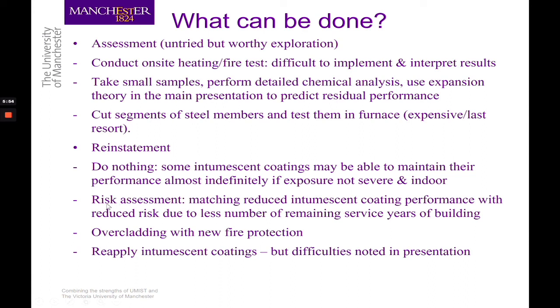The second one is to match the reduced performance of intumescent coatings with the reduced overall risk of fire, because a building is designed for a period of life, and as the intumescent coating is used for many years, the residual total risk of the building under fire is less, proportional to the number of years, so that we can match the residual performance of intumescent coatings to the residual total risk.